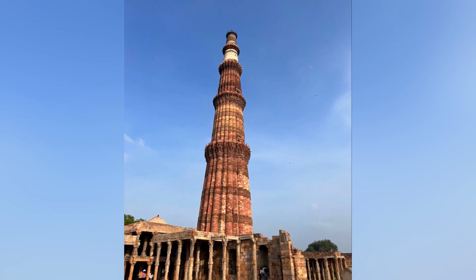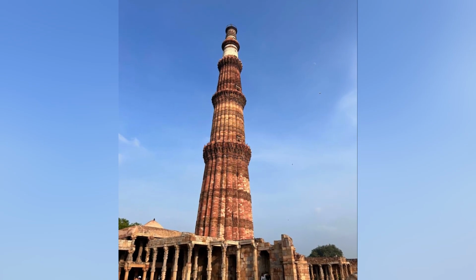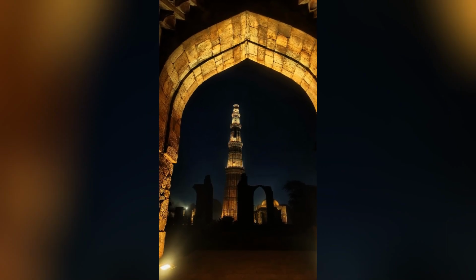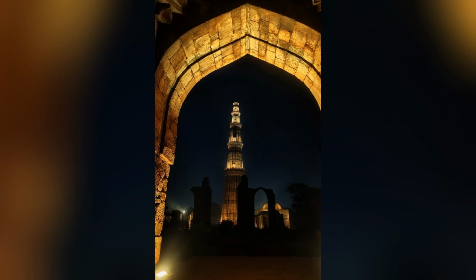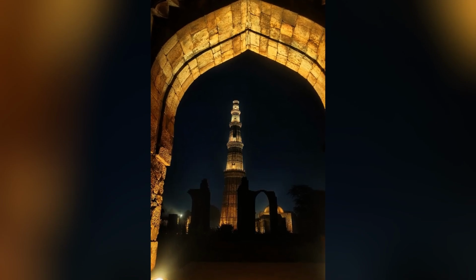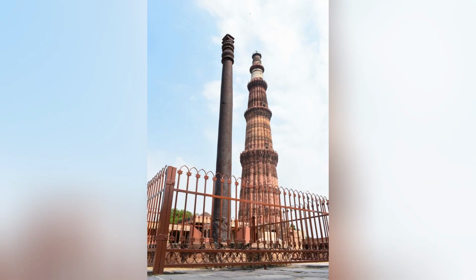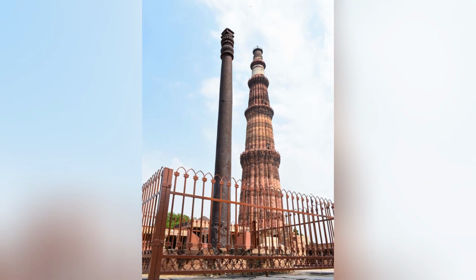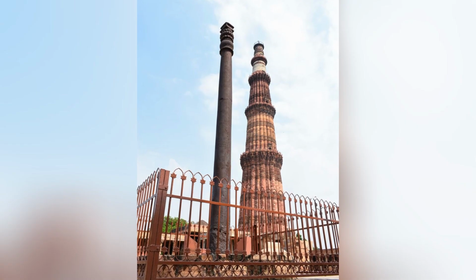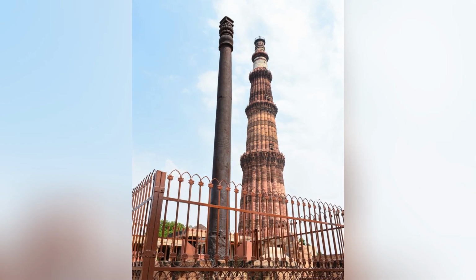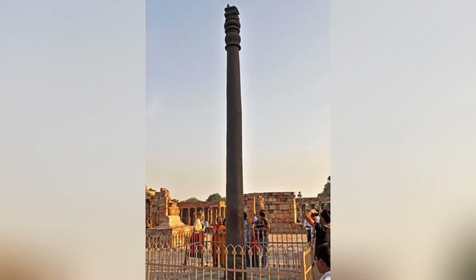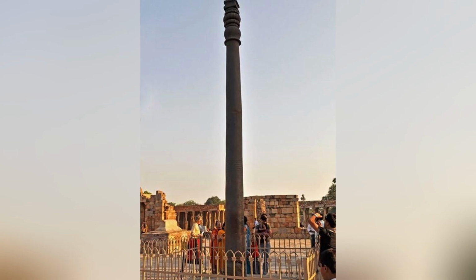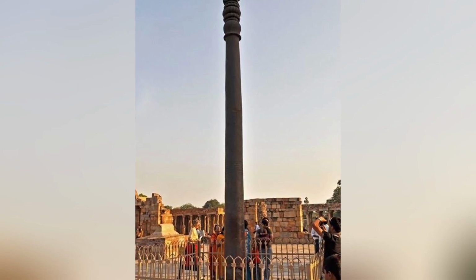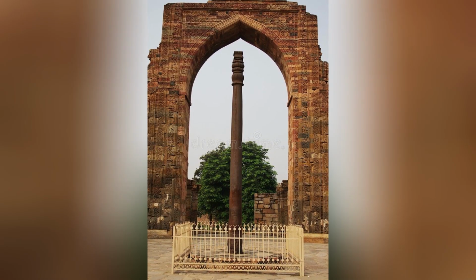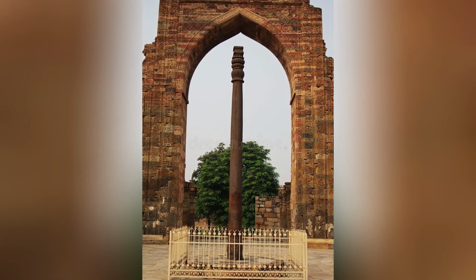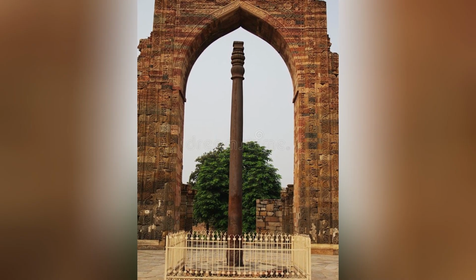The seventh major track of investigation has been the study of the pillar's microstructure, which provides information about the specific techniques that were used in its production and about the thermal and mechanical history that the iron has undergone. The microstructure of the pillar's iron, which has been examined using optical microscopy and scanning electron microscopy, is characteristic of bloomery iron that has been extensively forged, with a matrix of ferrite grains, the low-carbon phase of iron, interspersed with inclusions of slag and with bands of phosphorus-enriched iron that reflect the specific conditions of the smelting and the forging